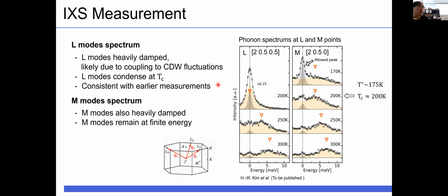And the M mode is also heavily damped like the L mode, perhaps because of the same reason, but it remains at finite energy near 175 Kelvin, where an additional phase transition is expected to happen. We can find a clear shoulder in the 170 Kelvin data. It means that the M phonon does not condense. One can ask, what's the big elastic peak in the 170 Kelvin data? It's a Bragg peak because M points become zone center after the phase transition. It is an allowed peak, but it's a very small Bragg peak. So anyway, it's not condensation of the M phonon.